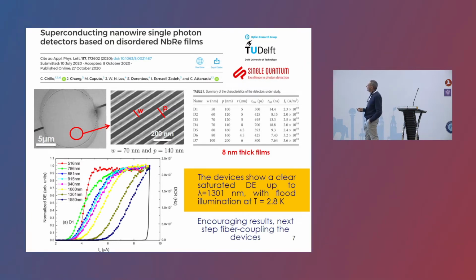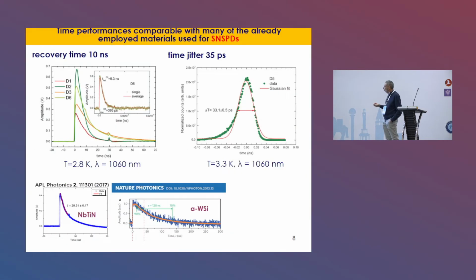They did, and the results were quite encouraging. The experiment was done on 8 nanometer thick films, and what was nice for us was that the recovery time and also the time jitter for this system were quite low, and they were comparable to the performances that have been obtained on very well-established materials for superconducting single photon detectors, like niobium titanium nitride, or amorphous tungsten silicide.